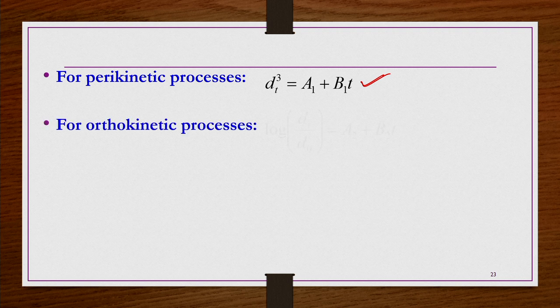For perikinetic processes, the size of the particle, let us say after time t, if you want to increase it to size dt, then dt cube equals a1 plus b1 t. That is a suitable equation to represent this perikinetic process in general. For orthokinetic processes, you can represent the equation like this. These equations are already derived and provided by several researchers, and they are available in books. So for orthokinetic processes, they can be written as log of dt by d naught equals a2 plus b2 t. This d naught is the initial size of the particle, dt is the enlarged size of the particle after time t. Okay, this a1, b1, a2, b2 are constants.